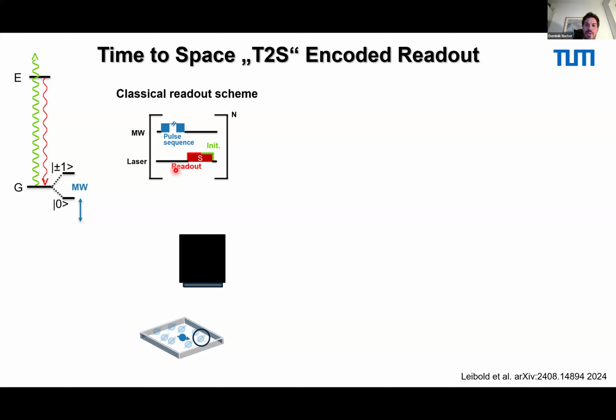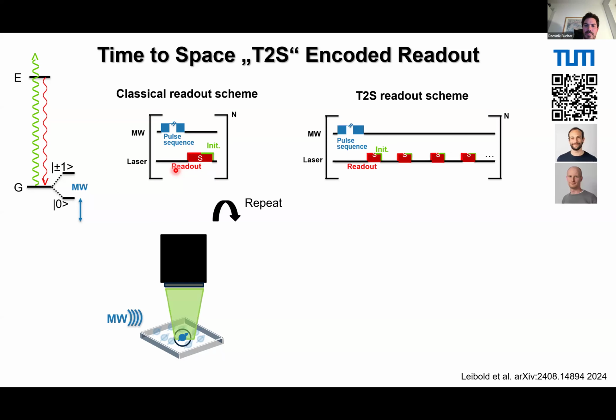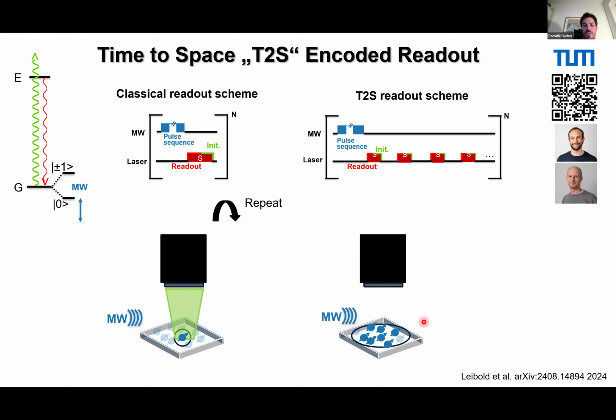And now the very simple, but I think powerful idea was, why not just apply the pulse sequence? Of course, keep in mind, typically the pulse sequence is much longer than your optical readout and initialization. So why not do the pulse sequence on an entire volume, or let's say region of interest? So we would manipulate all of these spins. What we of course would also do in this case, typically we don't apply the microwave only on one spin. So typically we would do it on, let's say, a couple of hundreds of micrometers. And then basically we read out. So we manipulate all of the spins, and then we read out these NV centers very quickly, one after the other at different positions. Okay.